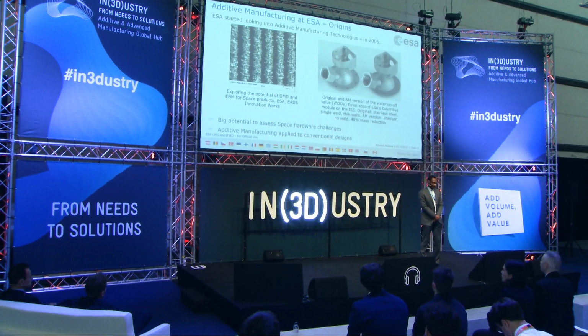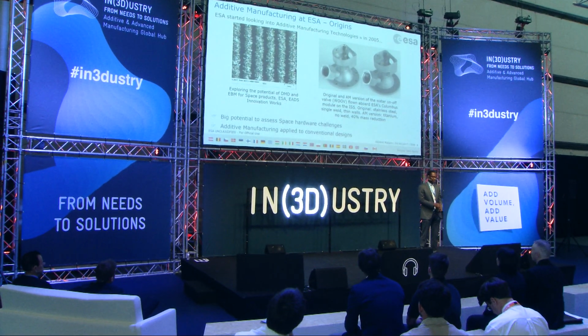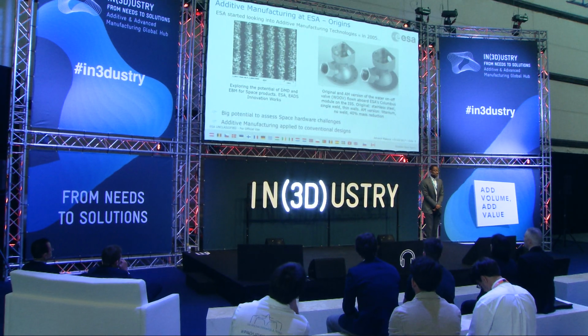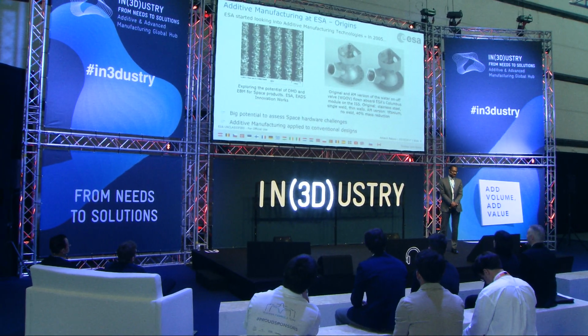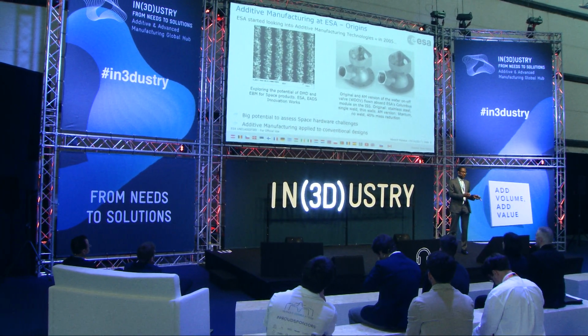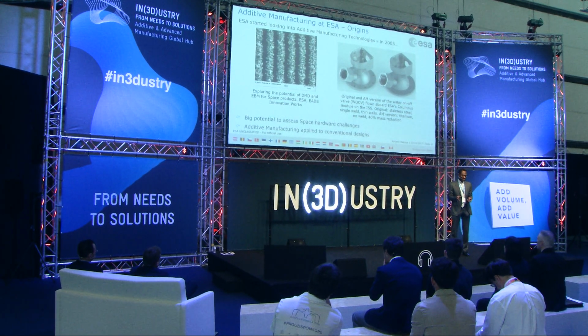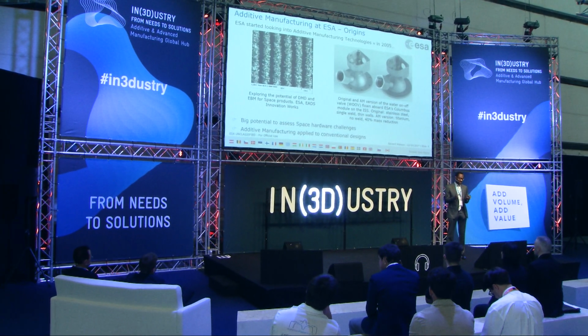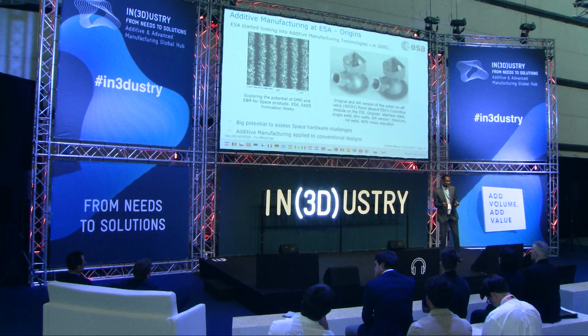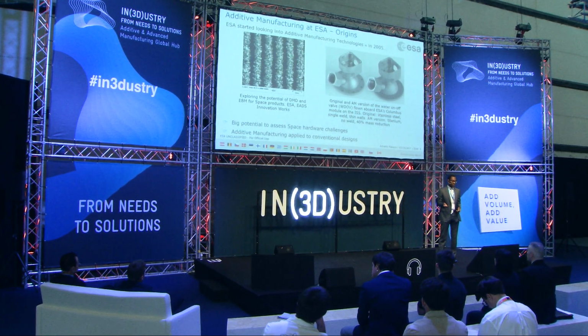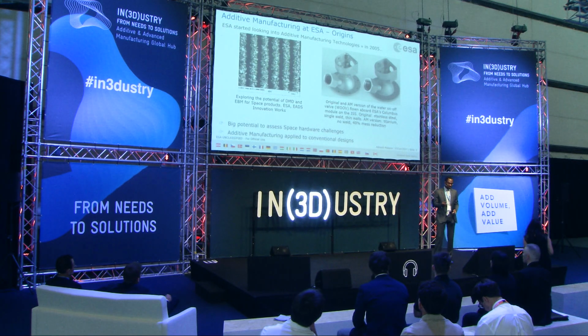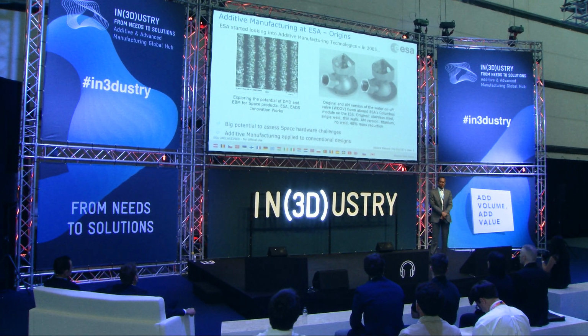On the right, you have a part which is a water on-off valve, which is on the Columbus Laboratory on the International Space Station. And my colleague looked at replicating the design, but changing the material from stainless steel to titanium. He managed to reduce the weld, eliminate the weld in this part, and achieved a 40% mass reduction.